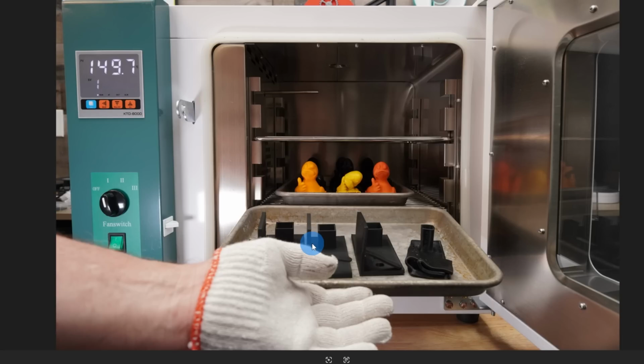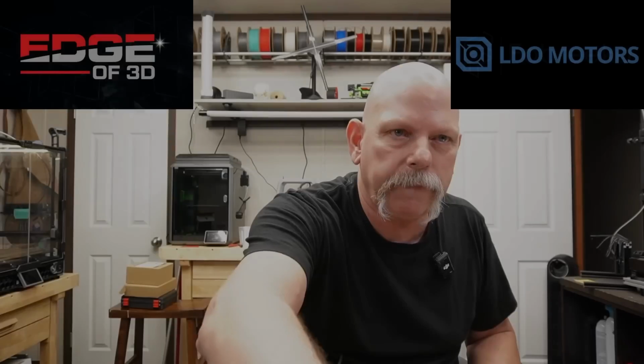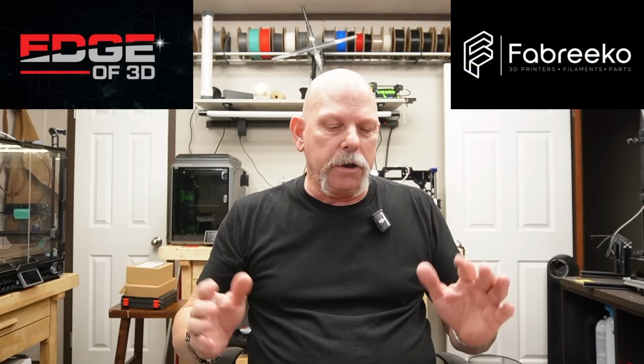The Polyterra PLA held on surprisingly well, other than the arms sinking down, and the walls started to come just a little bit off of 90 degrees. And the High Temp PLA is being blocked by my thumb, but you have to remember that tray right there is 150 degrees Celsius, and those are just lightweight cotton gloves, so I couldn't really hold it too well. But we'll look at these up close right now. So there you go.